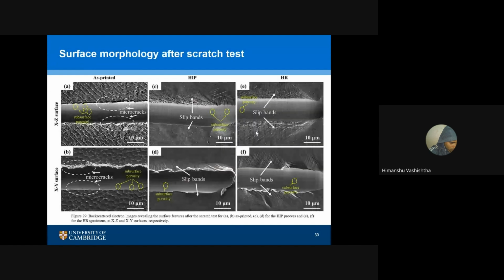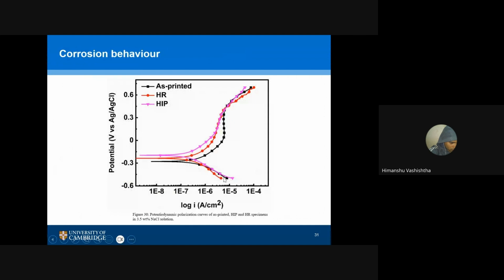So the justification for this as-printed case is because it has the lowest corrosion resistance, it has a lot of defects. When your material is trying to passivate, the passive layer will break down at the defect points, and that's why your corrosion resistance is lower in the as-printed case.